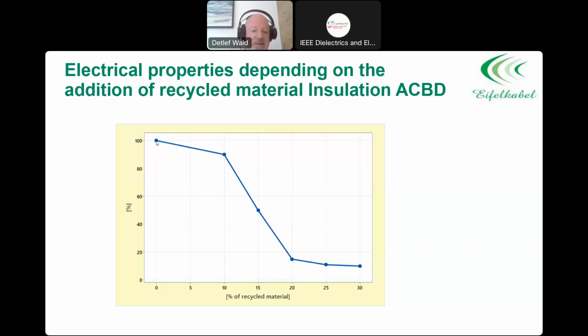So naturally at 0 you had 100%, and here was a significant drop in it, which we assume is due to the cutting, where we had metal contamination in the polypropylene. So for insulation compounds, to add polypropylene again as insulation into low voltage cables, up to a certain percentage, up to 10%, it's still possible, but then you have to be careful because you are probably degrading it quite heavily due to metal contamination, and it's not recommended.